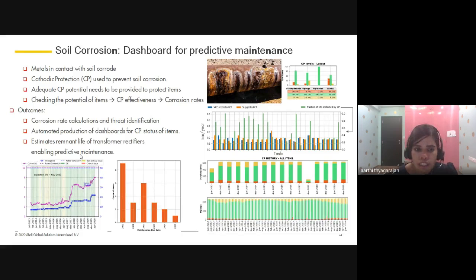One of the few challenges here was the prevalent models for soil corrosion used within Shell, which did not have features to accept the time series of the historical inspection data, which is available for most of the assets. Thus, to take advantage of the wealth of inspection data available, it was necessary to create a modified method approach within the framework of VCE, which uses some of the technical logic in the existing tools, but with the added alignment with the subject matter experts. Now, we faced major challenges, and one of them was as simple as how do we extract and clean the data, and how do you apply different data cleaning strategies based on the actual domain knowledge.